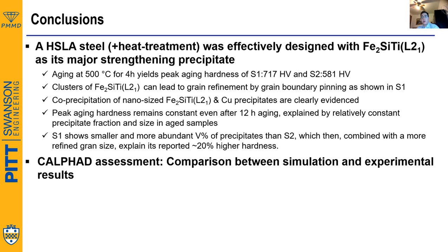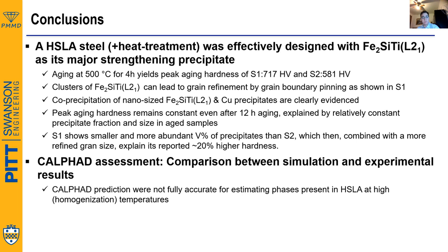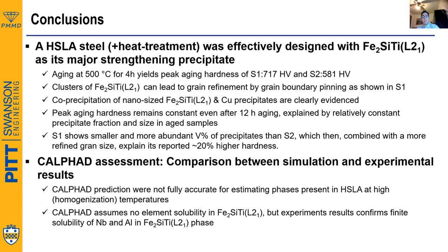Lastly, we can quickly point out a few comparisons between the simulation and the experiment results in order to assess the efficiency of CALPHAD at predicting these systems. We see that CALPHAD is not fully accurate at predicting the phase fraction in HSLAs. This is mainly related to the showing up of the L21 in the homogenized sample, the S1 homogenized sample. But this is tied up with the fact that the L21 is modeled as a line compound with no solubility,